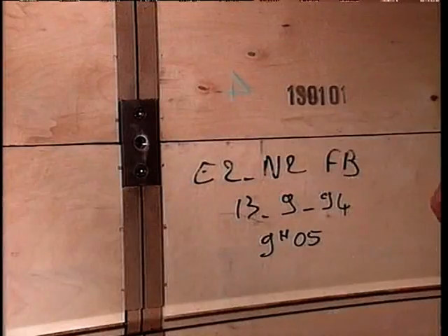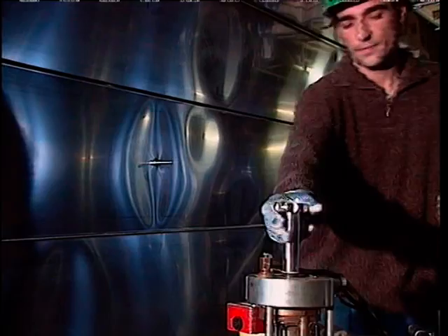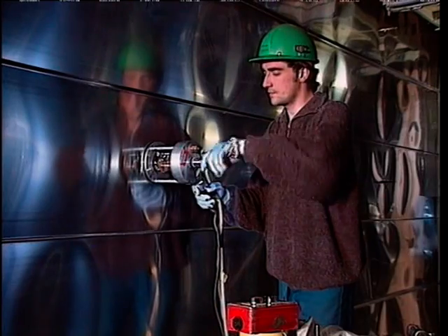The bases that we see behind the metal foil were placed temporarily under the Invar membrane and screwed onto the stainless coupling plates. The base allows hole punching of the strake in order to screw the collar studs in. These stainless steel collar studs will later be used to anchor the primary insulation boxes. Their base is welded onto the membrane by an automatic TIG process rotary machine.